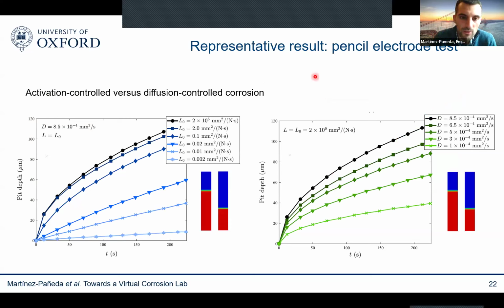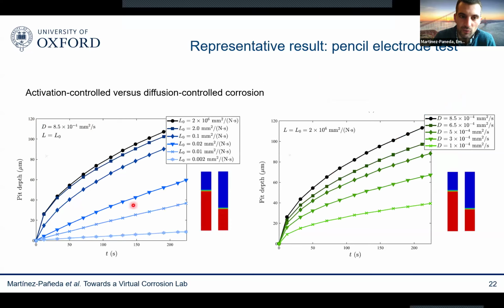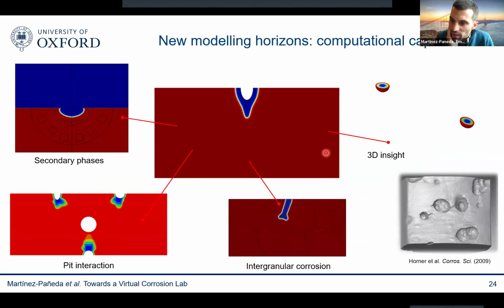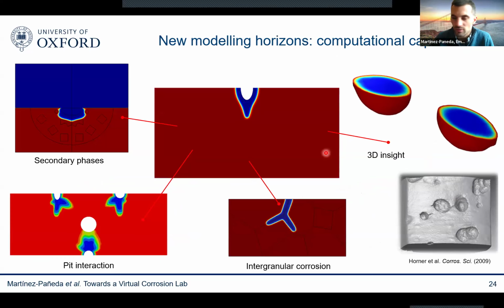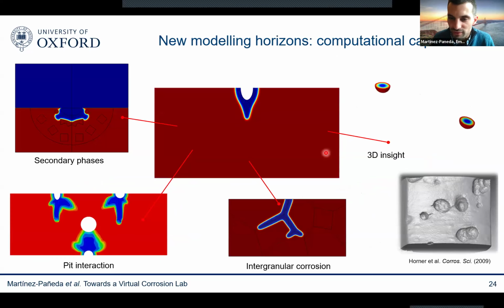And you can see this here. So this mobility coefficient, as I ramp it up, as I increase my corrosion current density, I go from the linear behavior of activation control corrosion to the parabolic behavior of diffusion control corrosion. And this means that when I'm in this regime where the corrosion current density is high enough, then of course my predictions are going to be quite sensitive to the diffusion coefficient. So this is another takeaway. I mentioned before, we have very complicated boundary conditions changing in time and space. We don't need to worry about those. All those phase field corrosion models can naturally capture the transition from activation to diffusion control corrosion. But of course, I don't want to focus on 1D problems. Most corrosion failures are not 1D.